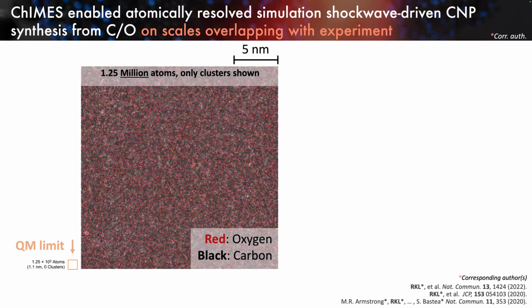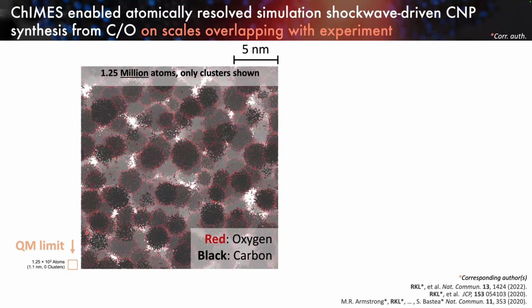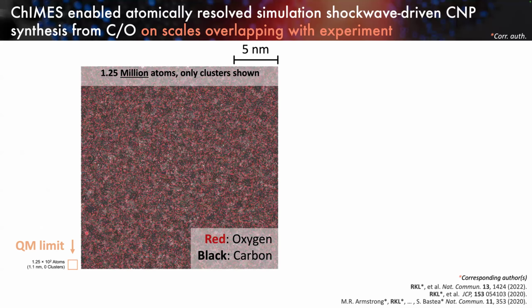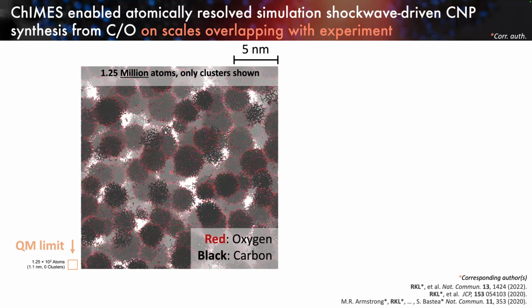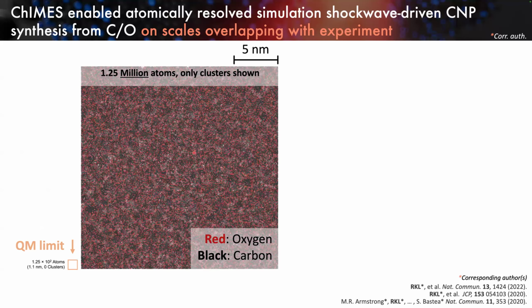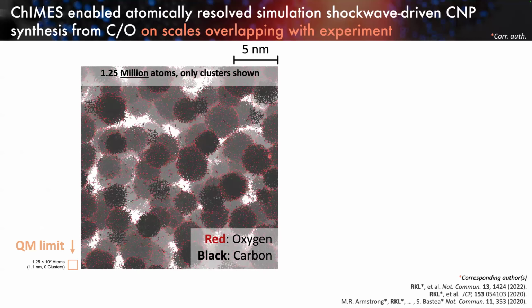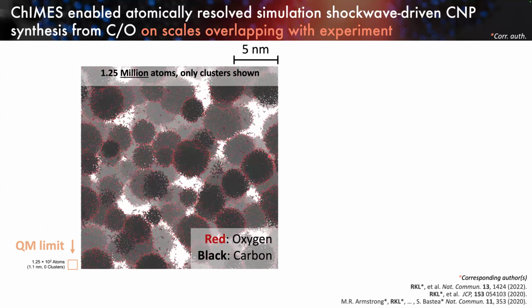Okay, so we take the chimes model that we built and run simulations where we've now scaled up to over 1 million atoms. When we do this, a very different picture emerges. Looking at this image, each little red dot is an oxygen atom, and the little black dots of equivalent size are our carbon atoms.